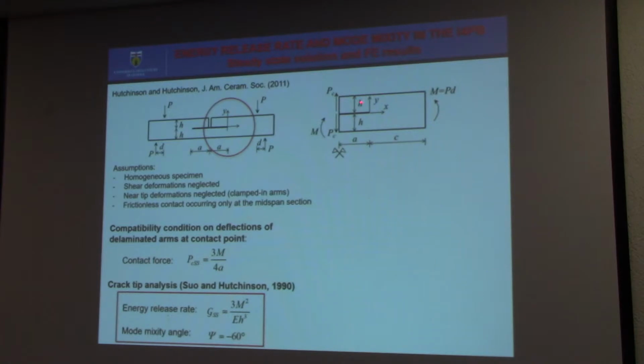Now, based on this, they calculated the transverse displacement at the midspan, and imposing a compatibility condition on the transverse displacement of the two delaminated arms, they obtained the contact force. And then by applying classical methods, they defined the energy release rate and the mode mixity angle. And this solution is again a steady-state solution. Energy release rate and mode mixity angle are independent of the crack length. And the mode mixity angle is around minus 60 degrees.